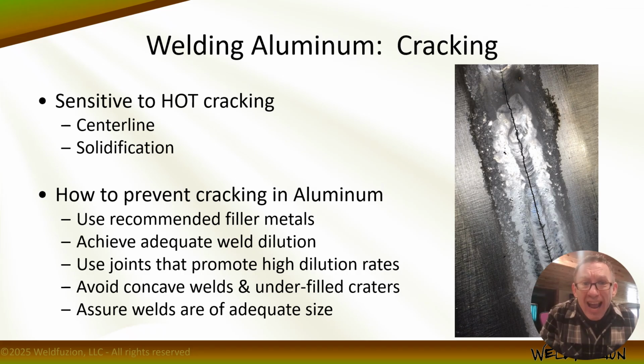Many alloys rely on adequate weld dilution, or the mixing of the base and filler metals in the weld pool, in order to prevent cracking, even with recommended filler metals. This is another factor in filler metal recommendation for aluminum, and joints that promote high dilution are also recommended so the resulting admixture has the right ingredients to resist cracking. Welds that lack fusion or penetration are prone to cracking from inadequate dilution that limits the essential mixing of the base and filler metals. This often occurs at the start or end of a weld, especially with fillet welds, where cracks can often be seen propagating from the root right up through the weld, which I would refer to as a throat crack.